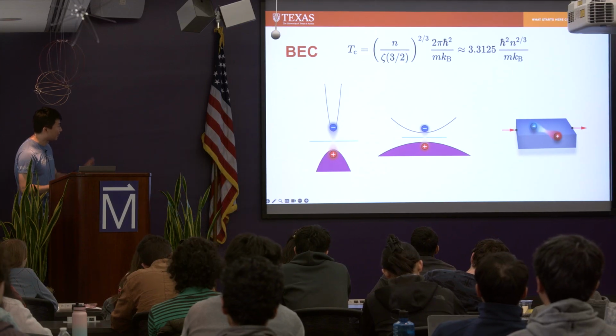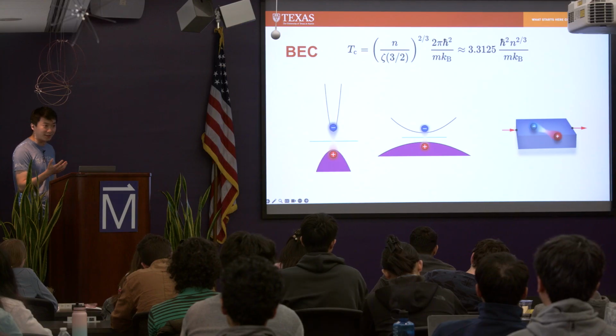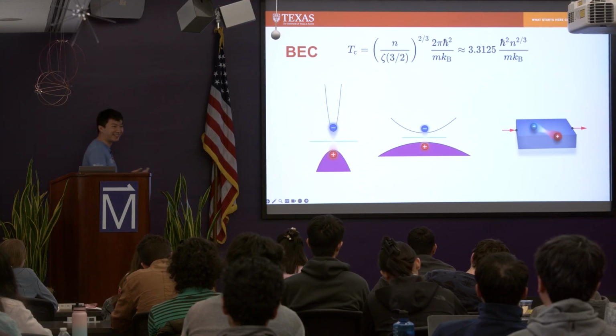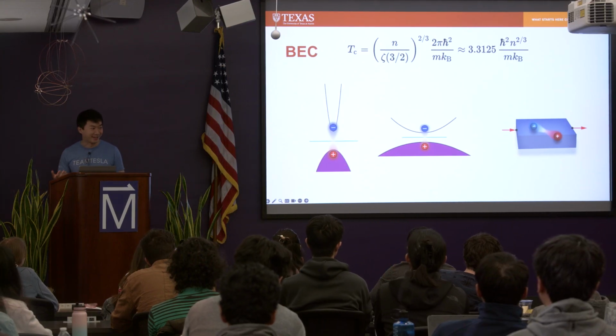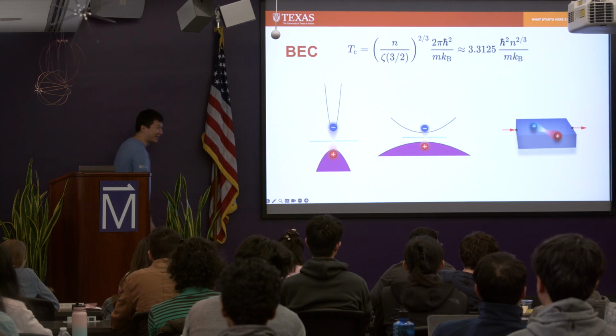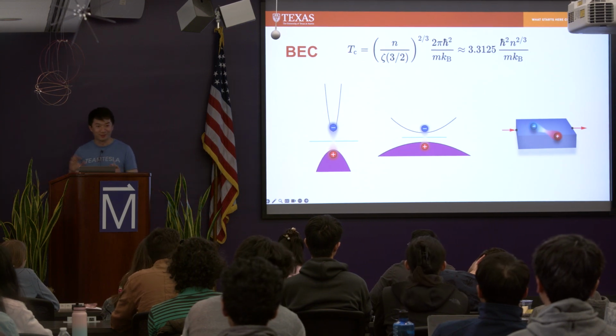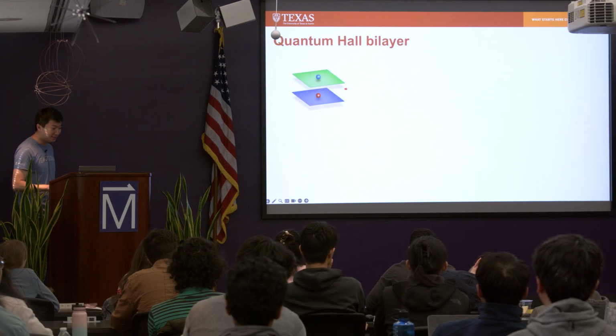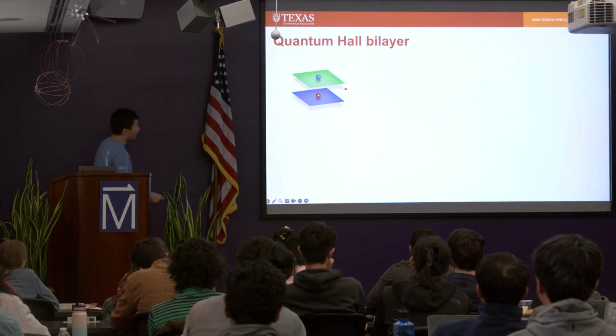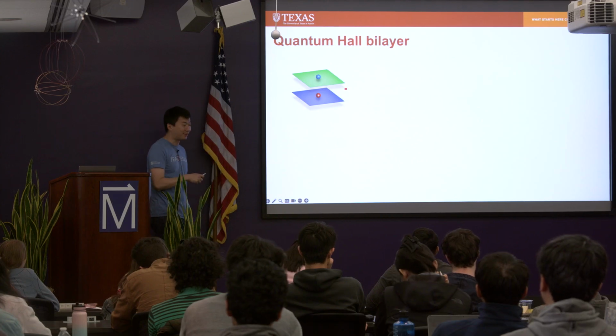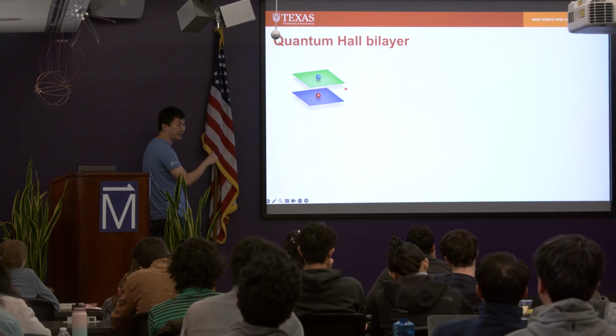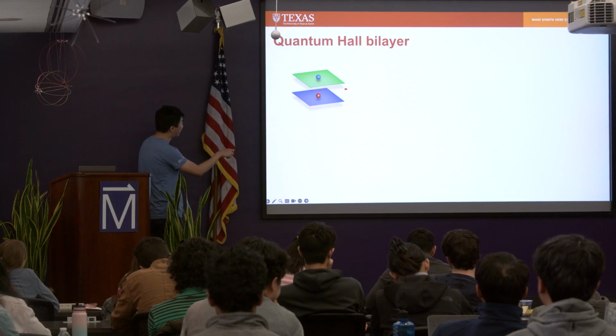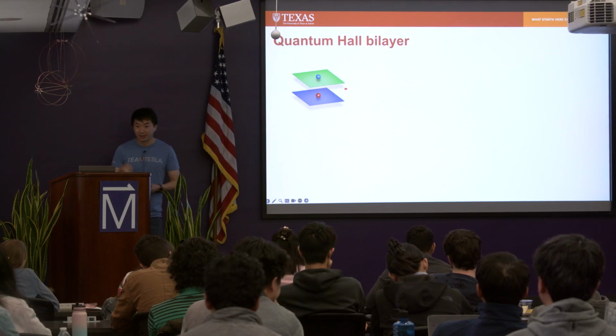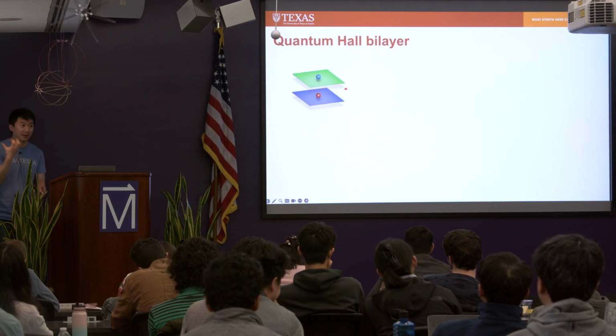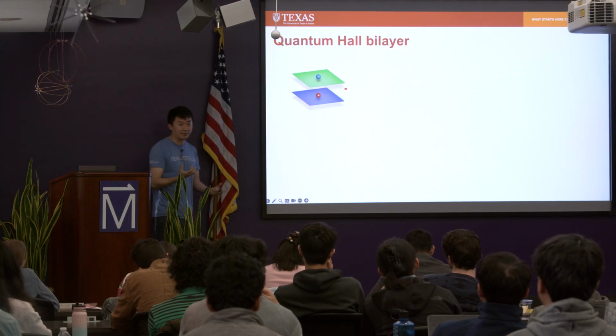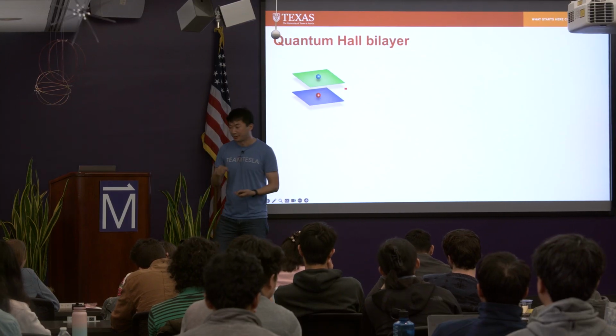And it turned out that all of these challenges can be fixed using a fairly easy method. When I say easy, that's in hindsight, right? It took decades of development. Allan MacDonald, Jim Eisenstein, and Greg here, for example, did a lot of groundwork to figure out this is the way to go. And the solution is a quantum Hall bilayer. You take two 2D electron gases, right? You put them really close to each other, but prevent them from tunneling. You put electrons in one layer and holes in the other layer, right? These are stable electrons and holes, and if you can get them to pair and form excitons, the lifetime is infinitely long, right? Because they cannot tunnel, okay?